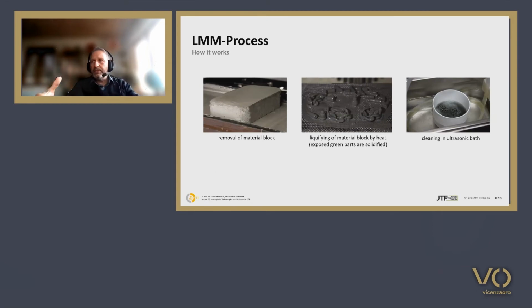So once your print job is finished, which can take a couple of hours, usually we do this overnight, you remove this material block. And again, I think the analogy of a butter block is quite nice because it's a solid block. You put it on a net, which you see in the middle, put it in an oven at 80 degrees. Then the non-exposed material liquefies, and the exposed samples, the green parts, which are solidified, they remain on the net. The other material you can directly reuse, but you have to mix it again because there are certain tendencies to demixing. So it's mixed again, but in general, there's no material loss at all, apart from what's remaining on that net and what's remaining on the surface. And you see the surface is kind of slurry-like. So what we do, we put them in ultrasonic baths with some special cleaning agent for a couple of minutes, and then you have your green parts.